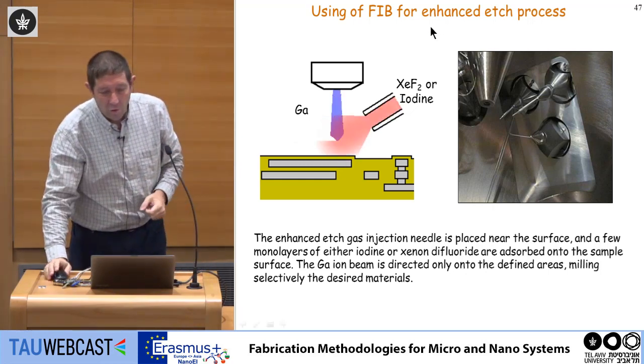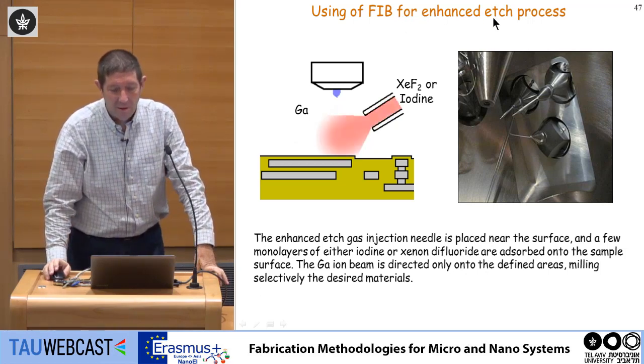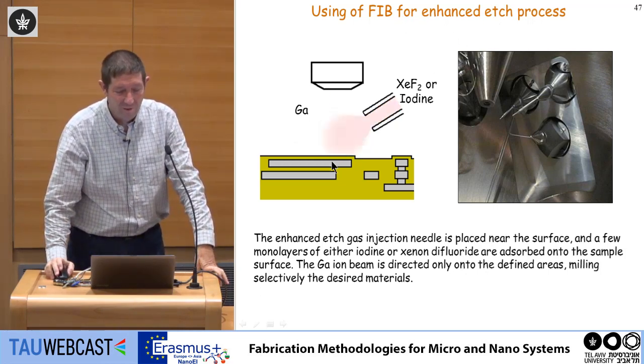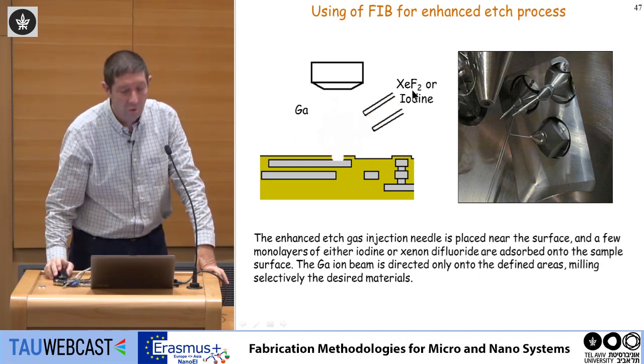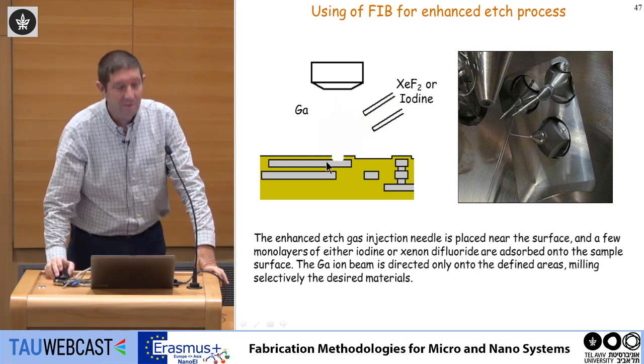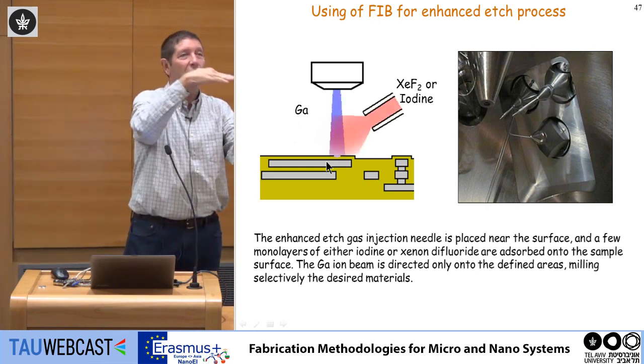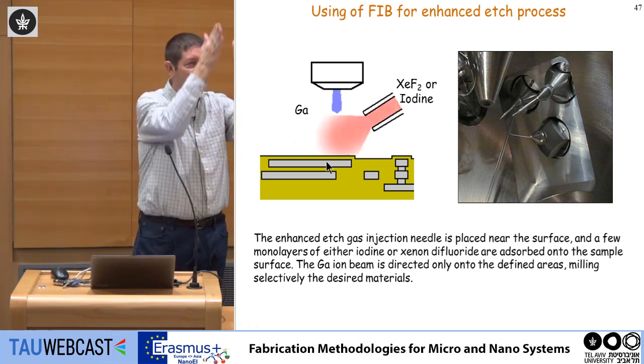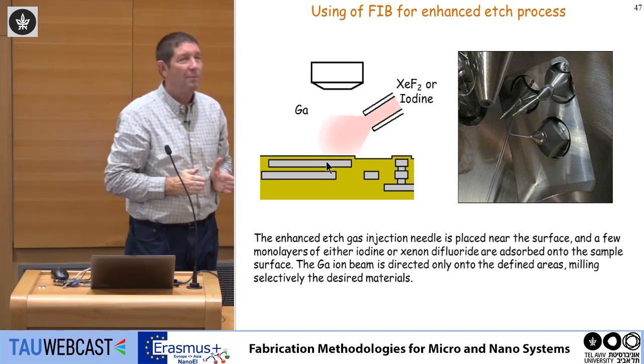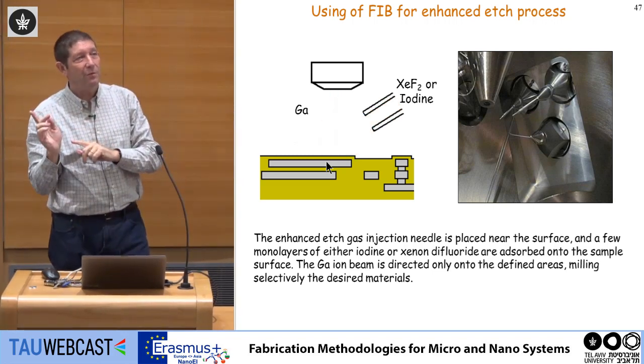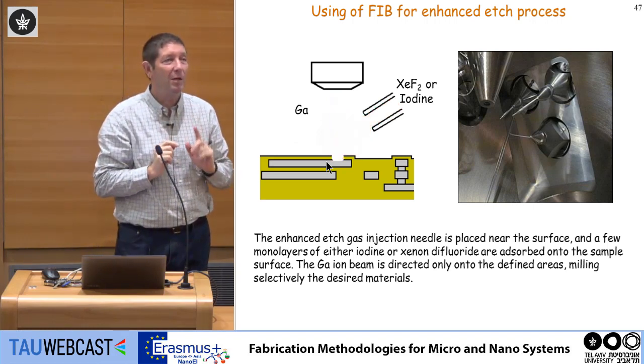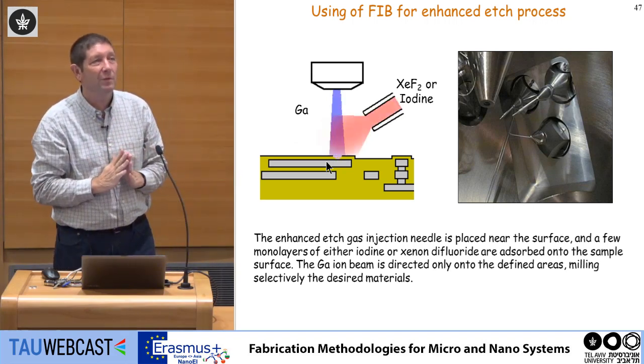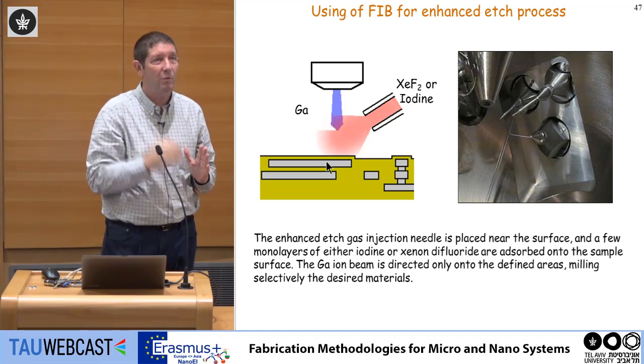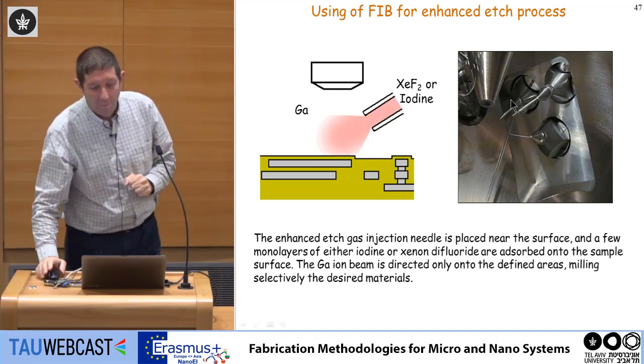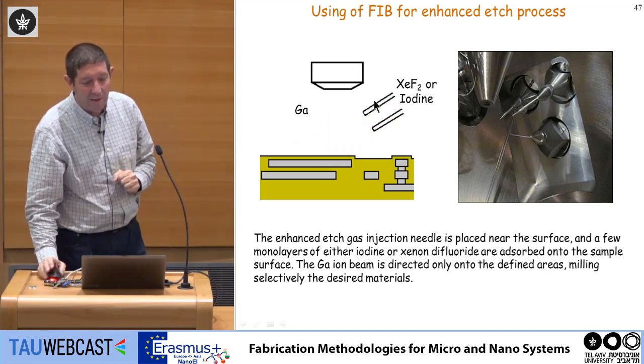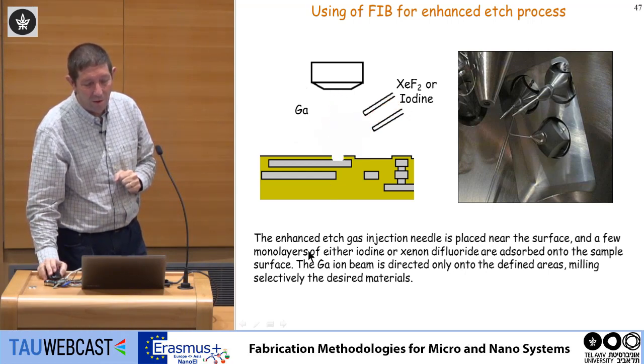And this is called ion beam enhanced etching, because now we have a very, very fast etching by the fluorine or by the iodine, and this etching is only perpendicular to the surface. So we can get a very beautiful etch by the iodine and by the fluorine, and not by the gallium. Here you have to control the amount of gallium. You don't want the gallium to etch the surface. You want the fluorine to etch the surface. But the fluorine or the iodine get their kinetic energy from the gallium beam.